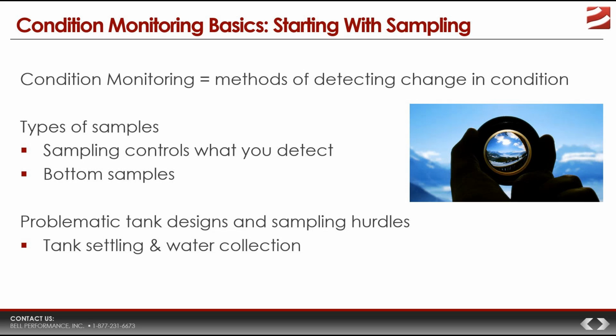And it's very possible that if you're using a dispenser sample to try to test for the presence of microbes, then you're not actually going to have a representative sample at all. In order to detect microbes, you don't need a dispenser sample, you need a bottom sample. But even if you get that, it is still remarkably easy to get a bad bottom sample that won't give you accurate results if you're trying to detect microbes.